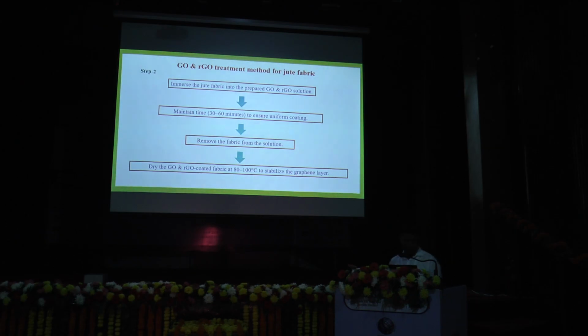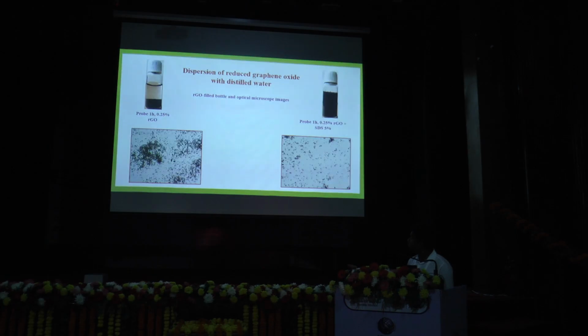Then step 2, immerse the jute fabric into the prepared solution of graphene oxide and reduced graphene oxide. Then maintain the time up to 30 to 60 minutes to ensure uniform coating. Then remove the fabric from the solution. Then dry the coated fabric. Then further stabilize the graphene layer.